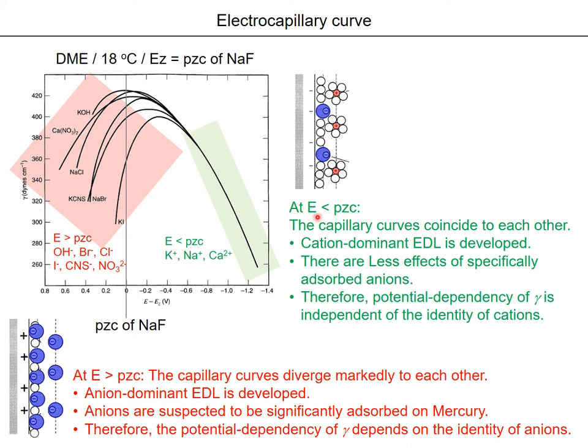At potentials more negative than the point of zero charge, the capillary curves coincide with each other like that. It looks like just one single curve. In this situation, a cation dominant electric double layer is developed. So you can find the cations here in the outer Helmholtz plane.